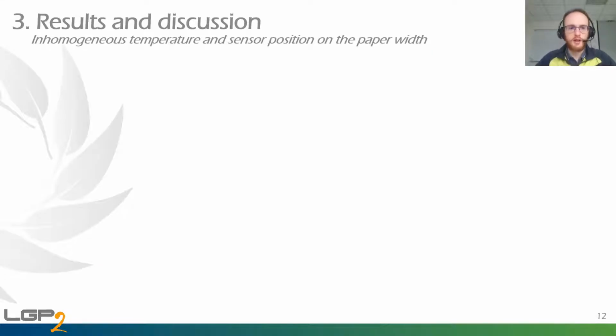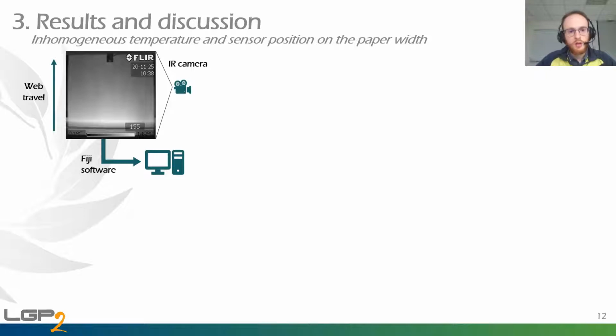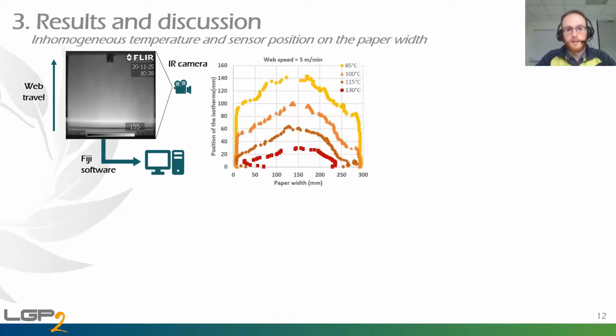Now let's check the inhomogeneous temperatures and sensor positions on the paper web. As I told you before, we took different infrared pictures, and then we used Fiji software to get the different temperature profiles. This represents this profile. So we have here the position of isotherms when 0 is the exit of the infrared dryers, and here the position on the paper web. I represent here 4 different isotherms between 85 Celsius degrees to 130 Celsius degrees.